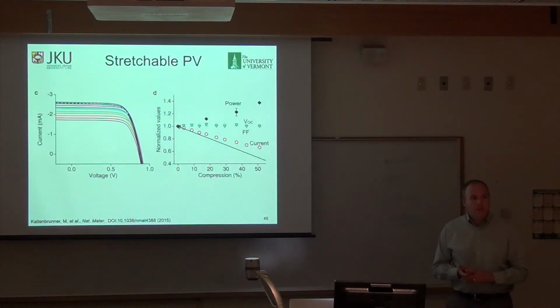It's a little bit surprising that this inorganic crystal, the perovskite, can withstand it, but we know that because the film is thin, there's not much stress in the actual semiconductor itself, so this is not too surprising. It's a nice demonstration that the technology is robust under this kind of deformation. These are the various stages of compression, down to about 50%, and then restretching to flat, and the device works exactly the same.